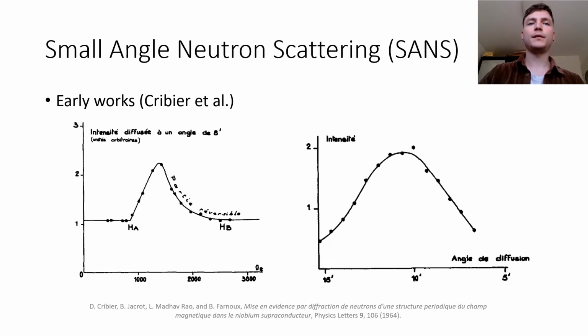At 4.2 Kelvin, the first critical field is at about 1400 Oersted, which is the unit for magnetic field in the CGS system, and Hc2 is at about 2700 Oersted. They used neutrons with a wavelength of about 4.7 angstrom with a resolution of 1.3 angstrom. And they used liquid hydrogen to multiply these neutrons by, I think, tenfold.